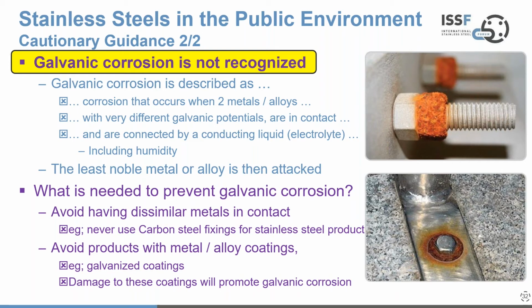And galvanic corrosion is described as corrosion that occurs when 2 metals or alloys that have very different galvanic potentials are in contact. And they then become connected by a conducting liquid, an electrolyte, which includes humidity. And then what's known as the least noble metal or alloy is attacked, and we can see that in the pictures, and it corrodes. So how do you avoid this? Well, avoiding having dissimilar metals in contact with one another is the obvious starting point. So never use carbon steel fixings for a stainless steel product. So in other words, don't have the carbon steel washer as shown in the bottom photograph. Always use a stainless steel washer, and then you get rid of the dissimilar metals problem.